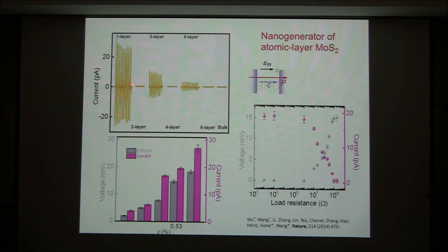This proves the idea that even-numbered layers have central symmetry and thus no piezoelectric output, while odd-numbered layers do not have central symmetry and do show piezoelectric output. So again, this is a typical nanoscale effect — an effect only one or three atomic-layer MoS₂ should have. If you build a thick sample, you don't have this effect.